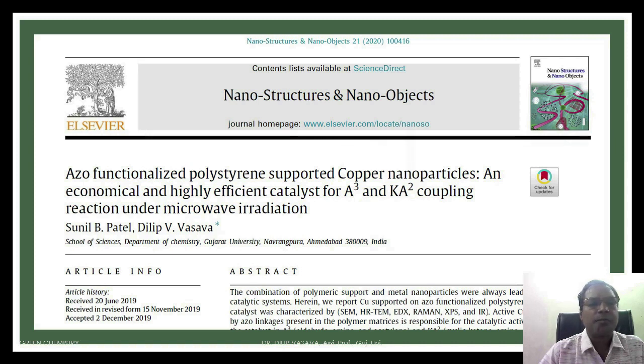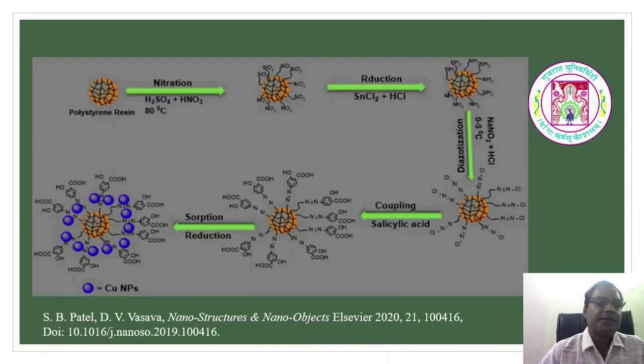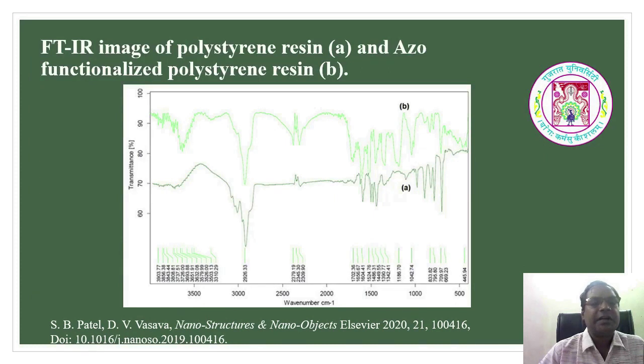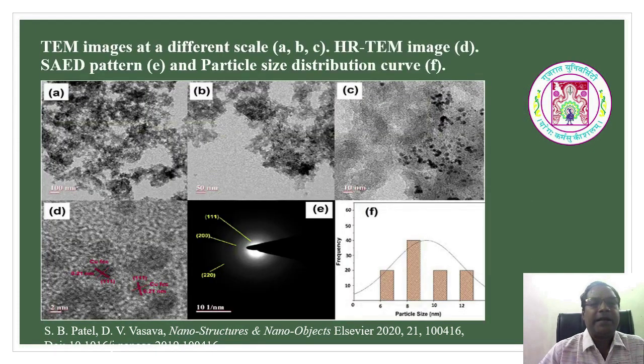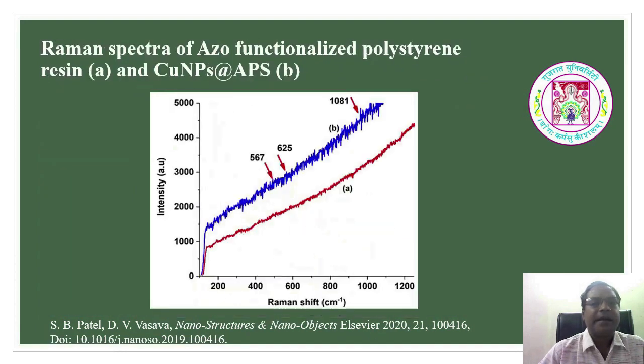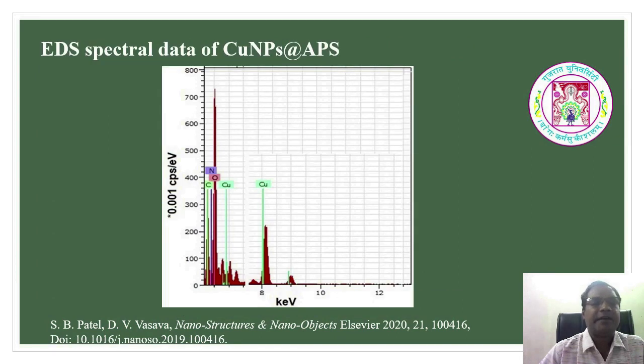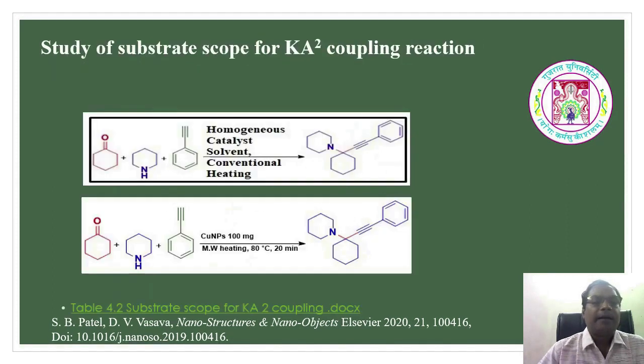Again here another work is reported by our research group, where it is also the coupling reaction, but here we have utilized the polystyrene as a support and copper nanoparticles are utilized. So this is the method to generate the polystyrene supported copper nanoparticles, and that catalyst was studied and characterized by the FTIR, then the SEM analysis, TEM analysis, XRD analysis, and the Raman spectra as well as the EDS spectra of the copper nanoparticles.